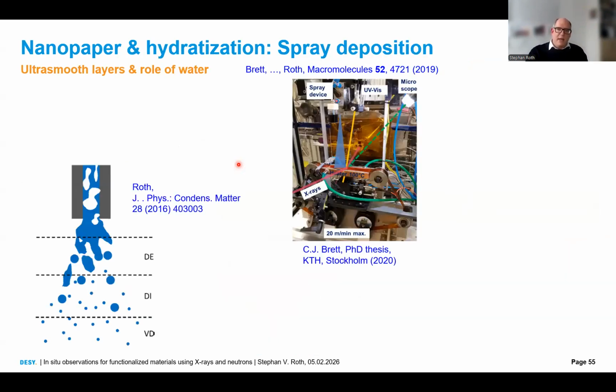Here we use spray deposition. We have a roll-to-roll coater which we can put into the beamline. We can coat up to 50 meters of any foil. Here is the spray cone. Here are the X-rays. We measure in situ the deposition on our samples. We have a microscope. We can even have a UV vis inside.